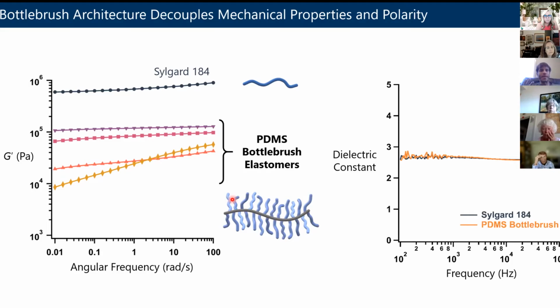You do this, though, without changing the polarizability. Remember, we said in devices, you want the material to be deformable, super soft, and polarizable. What you're looking at here is the dielectric constant, which is basically the polarizability at different frequencies. And you can see that your standard linear material and your bottlebrush material basically have indistinguishable polarizabilities. It's all just PDMS. So we're decoupling the polarizability from the mechanical properties using architecture.